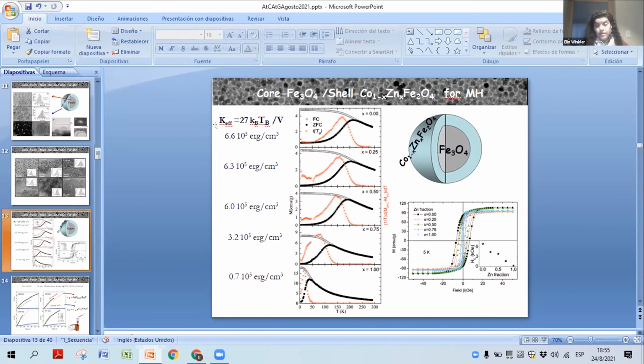the other measurement that can be done is the remanence measurement. In that case, you cool the system applying a magnetic field, you turn off the field, and then you make the measurement. It's another way to determine the blocking temperature and the anisotropy. And for that field, it's more or less the same. We do not observe many differences. Sometimes, if the system has a low magnetization, unfortunately, the measurement should be done with a larger magnetic field, at 100 oersteds, for example. But in this case, I think the data, with all that consideration, is right.